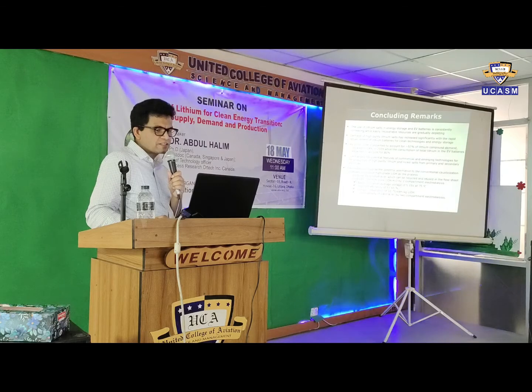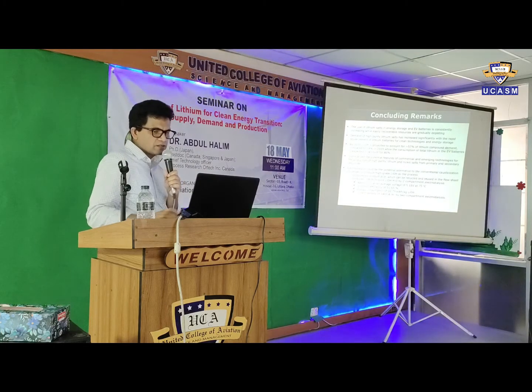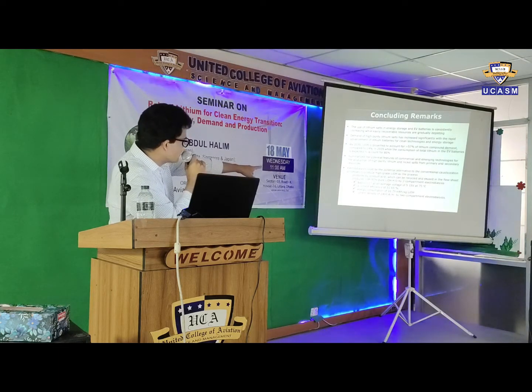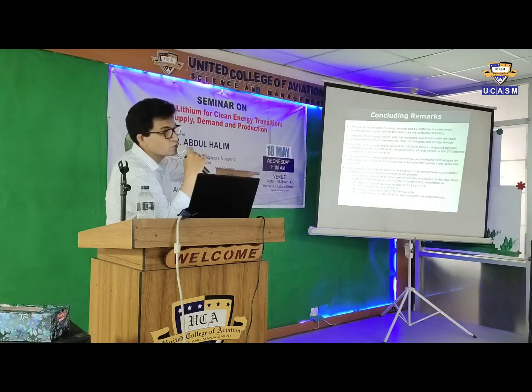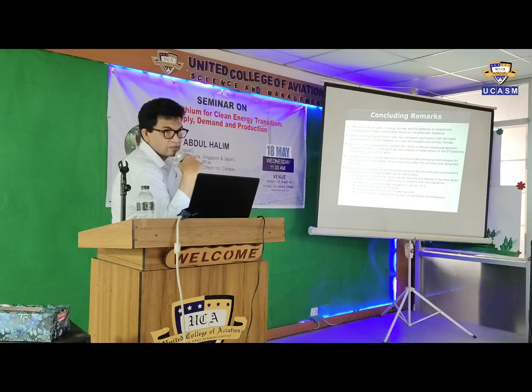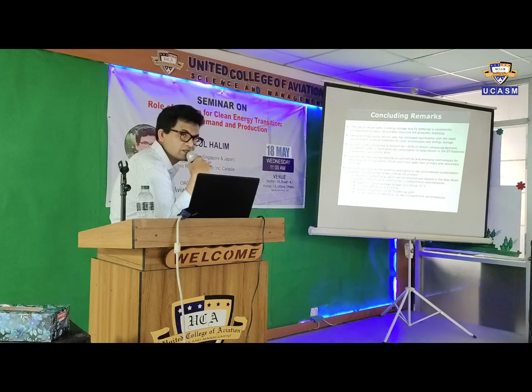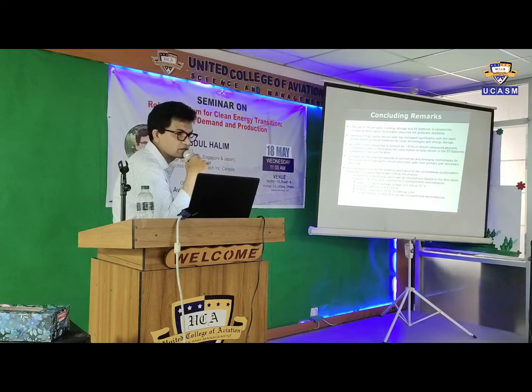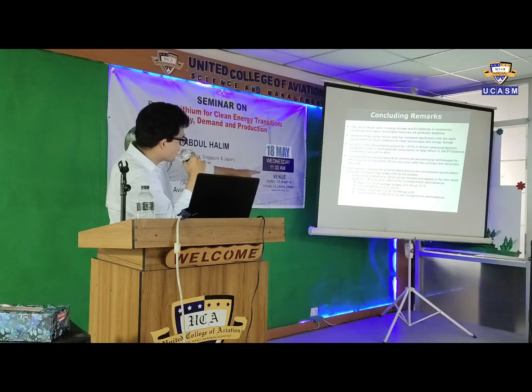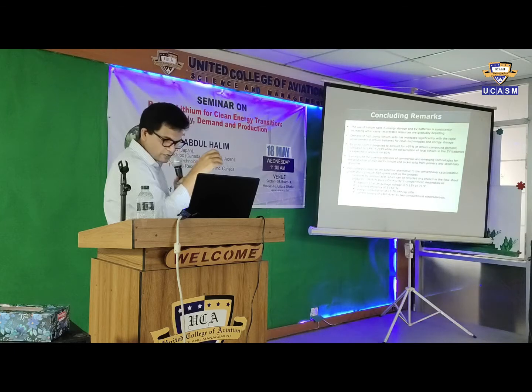The other thing is we produce 99.93% pure lithium hydroxide monohydrate by 2-compartment electrodialysis, using the last couple of bullet points you see. I did not discuss in detail, but you can see here what type of membrane, the cation membrane, gives us to make 99.9% pure lithium. There's so much business associated with it. We don't need to make the battery, but you can make this cation membrane by knowing the technology. It is so much market. The functional group, the reaction behind the chemistry, behind the metallurgy, behind the organic substance is different. So under these conditions and using these materials, we make 99.93% pure lithium hydroxide. That is very good for lithium-ion batteries.